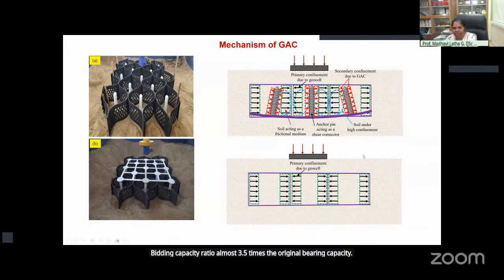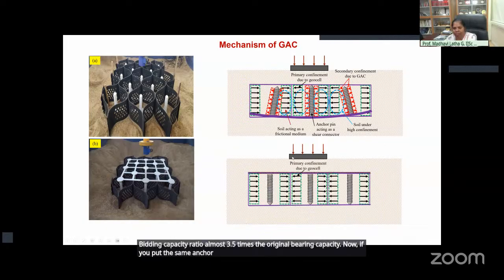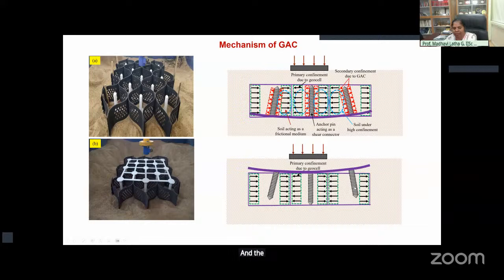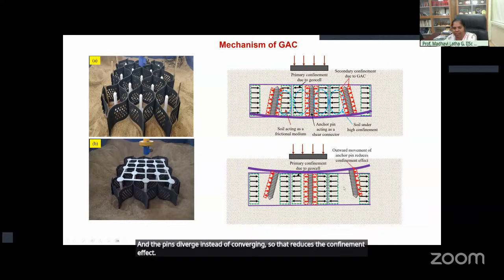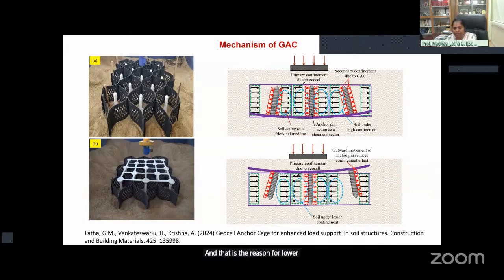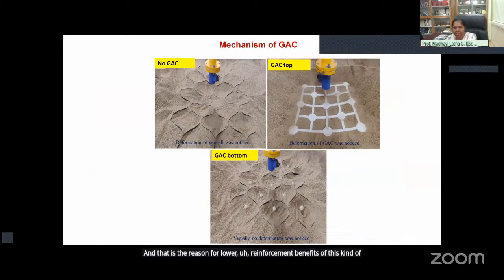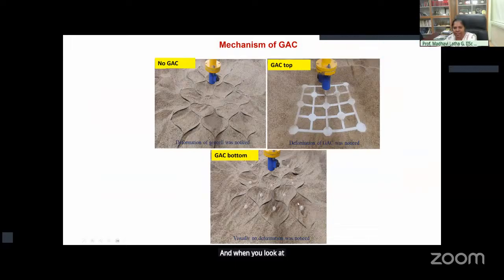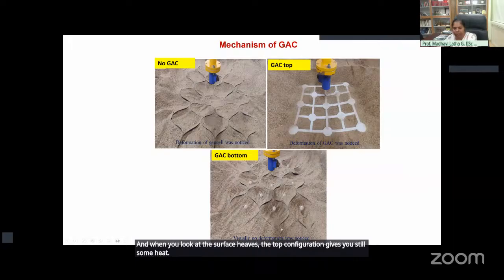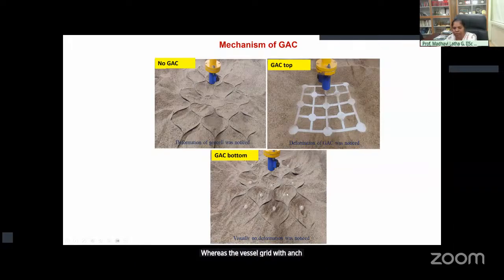Now, if you put the same anchor cage at the top, you are missing the geocell support, and the pins diverge instead of converging, so that reduces the confinement effect, and that is the reason for lower reinforcement benefits of this kind of configuration. And when you look at the surface heaves, the top configuration still gives you some heave, whereas the geocell grid with anchor pins gives you absolutely zero surface heave.